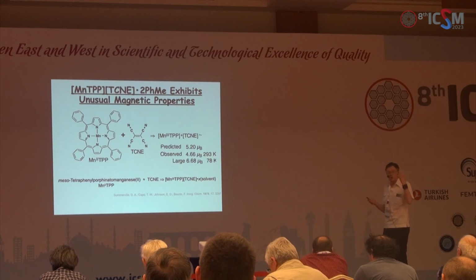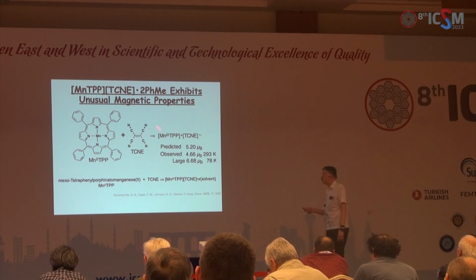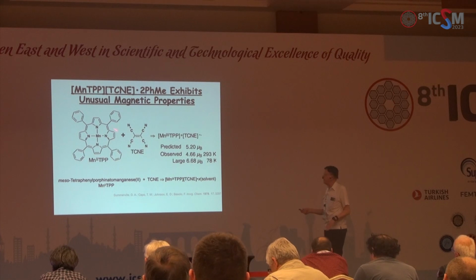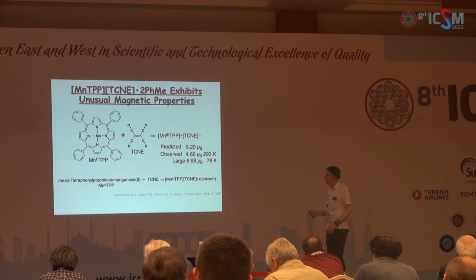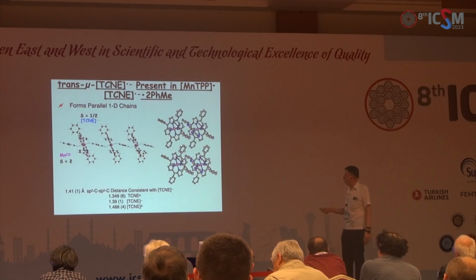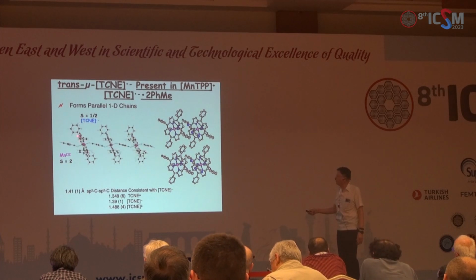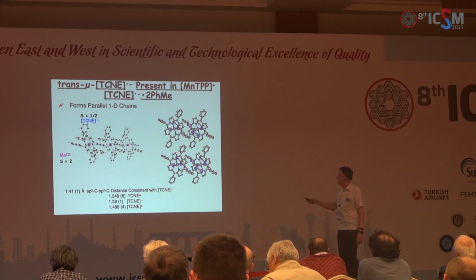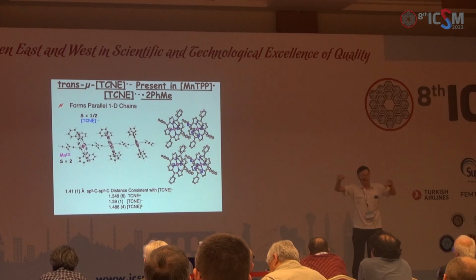It's manganese 2, and you mix it with TCNE. TCNE gets reduced, manganese 2 gets oxidized, so it goes to manganese 3. So there's 4 spins on the manganese, 1 spin on the TCNE, and it forms a chain structure: 4 spins, 1 spin, 4 spins, and these chains are parallel to each other.